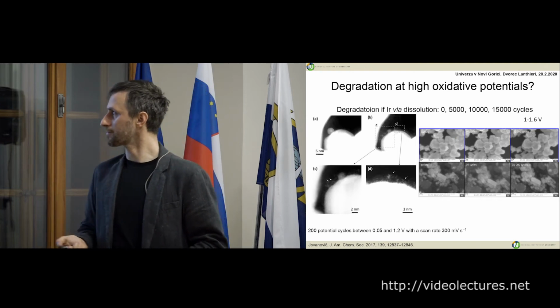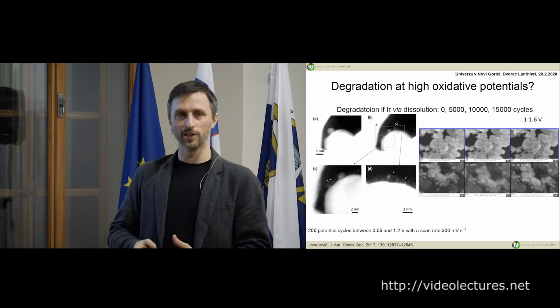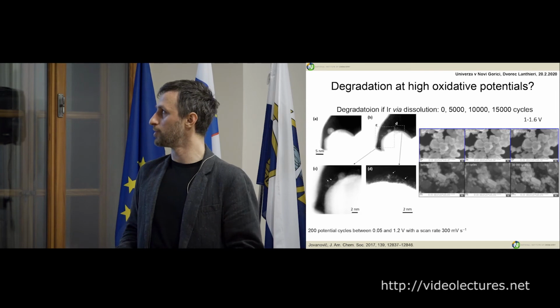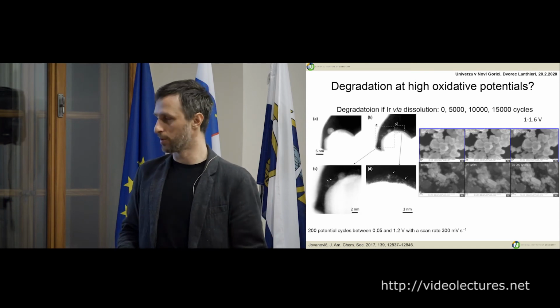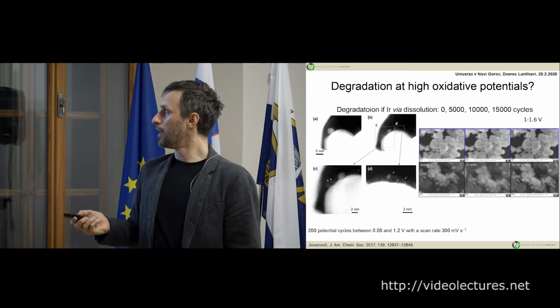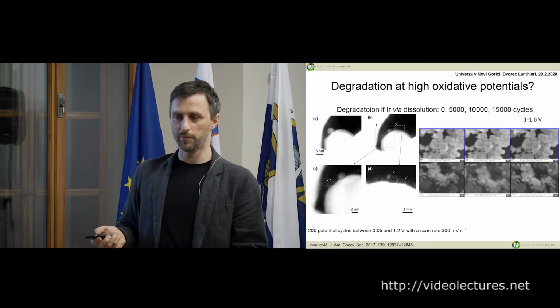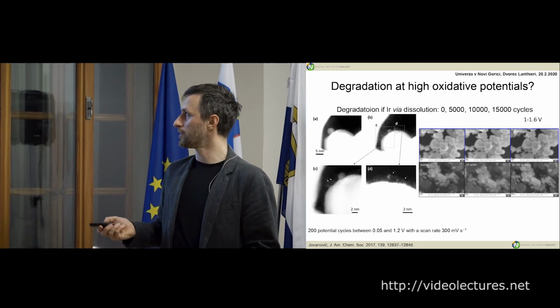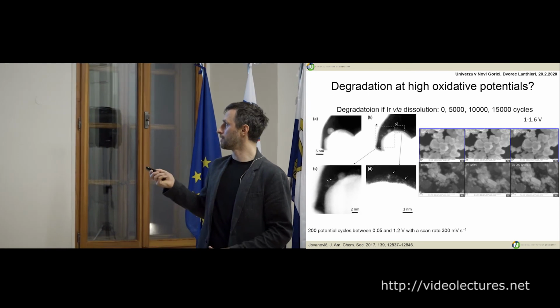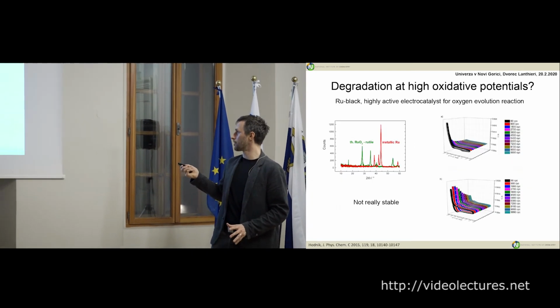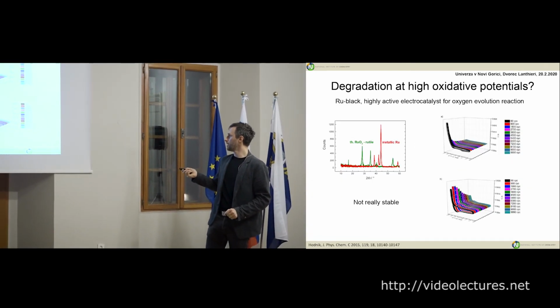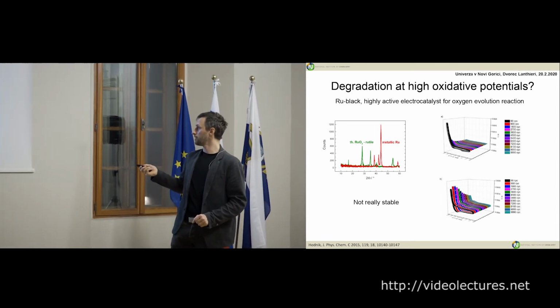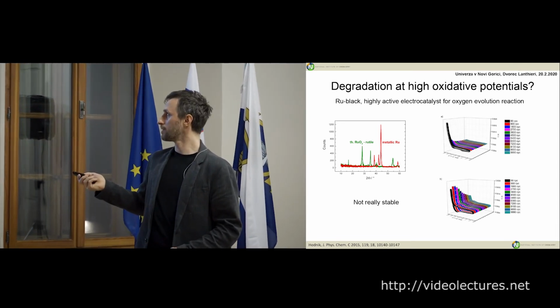SEM. But iridium has a lot still to do. This was just some initial studies that were also coupled with other techniques. For ruthenium, that some people say is a good catalyst, I say it's not stable. If you cycle, you can see the activity drop immediately. For the metallic and for the rutile, it's also dropping.